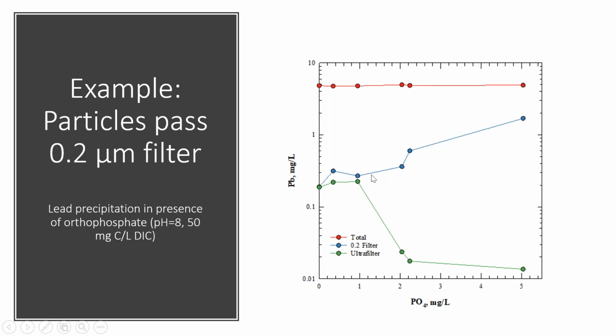But interestingly, as you shift from a mixed solid of big carbonate particles and small phosphate particles to a straight lead phosphate particle that's very small, it appears as if the lead concentration through a 0.2 micron filter actually goes up. In reality, it doesn't go up, because if you look at your ultrafilter, it goes way down. This is a perfect example of how particle size matters, because what you formed, and I'll show you some pictures later, is small nanoparticles of lead phosphate.